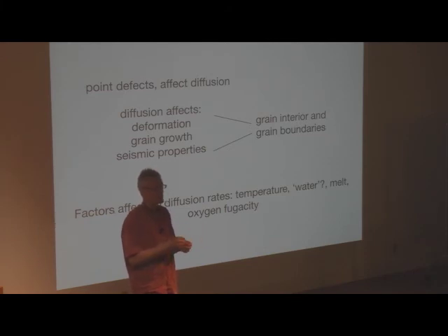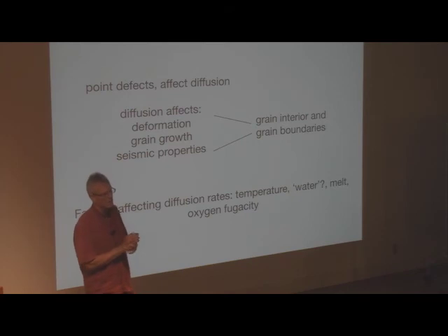But it's more complicated than that, because in iron-bearing olivine, as you vary the oxygen fugacity, you change the concentration of Fe3+, and that has a large effect. So Fe3+ is very important, it seems, and with it, oxygen fugacity. So that's where we are experimentally.